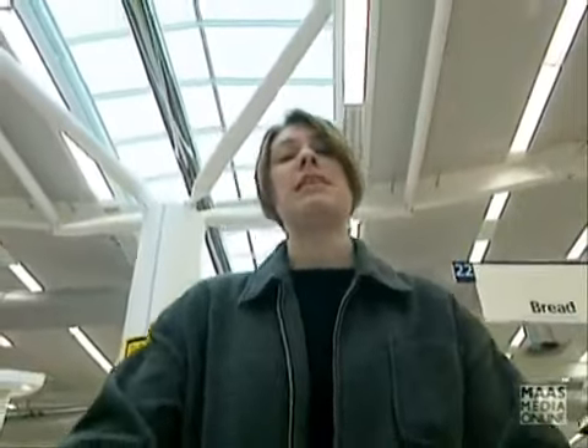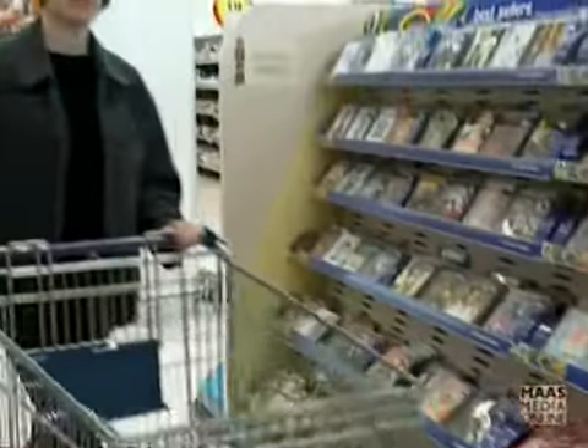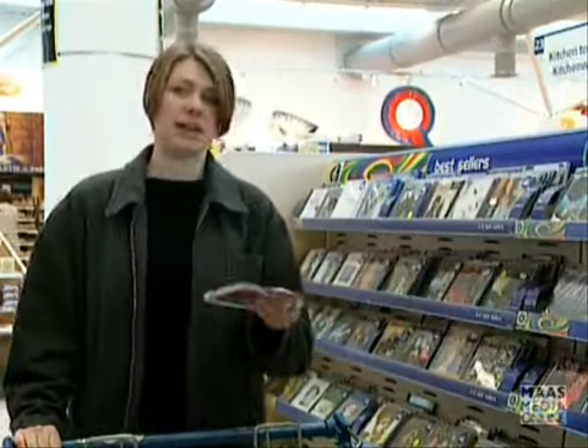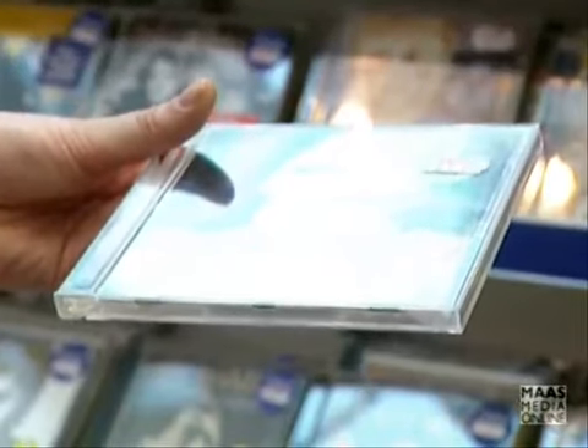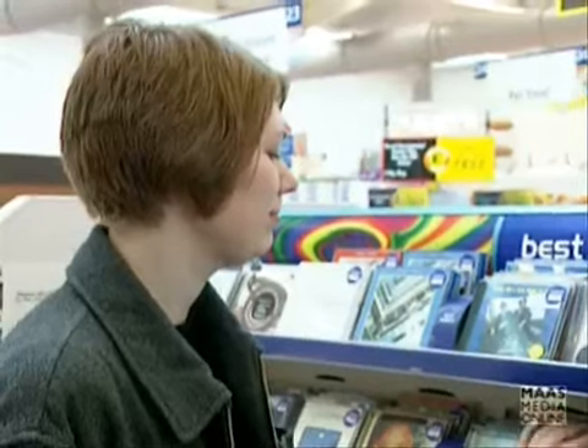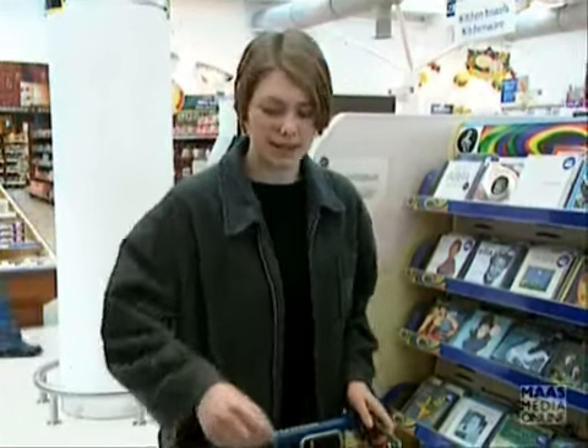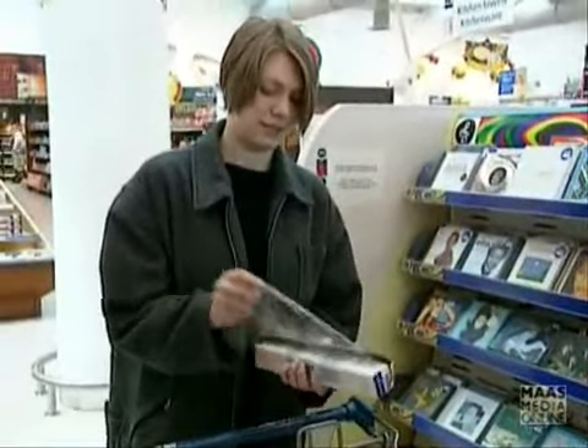But what if we want to take advantage of a polymer that's normally too stiff for the purpose we want to use it for? Take PVC or polyvinyl chloride, for instance. Normally, atactic PVC is a stiff and glassy polymer, rather like this polystyrene box. So how can we make it more flexible and stop it from becoming glassy? By including additives called plasticizers, we can make polymer chains much more flexible. Plasticizers are low molecular weight organic solvents, and they act as spacers and lubricants at the molecular level. They prevent chains from packing close together, and thus the formation of crystals. So by adding plasticizers to PVC, we can make it suitable for food wraps, like this, or for the flexible coverings on electrical cables.